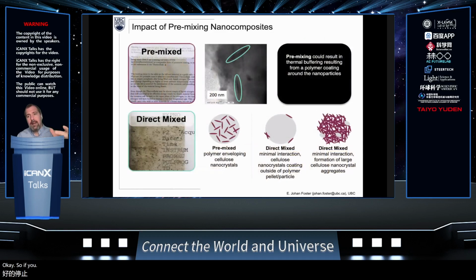so if you premix it, essentially what you're doing is you're using the polymer as a coating. Well, it's also the coating and the matrix, which allows the fairly quick dispersion within the larger matrix. Okay, so if you direct mix them, they start to aggregate. Cellulose loves to stick together, so the thermal stability isn't really buffered, and you get degradation.